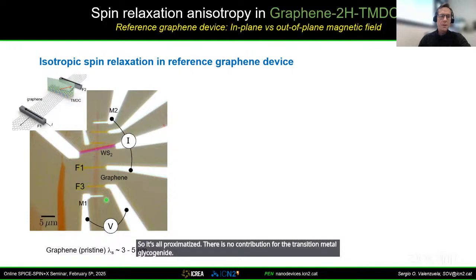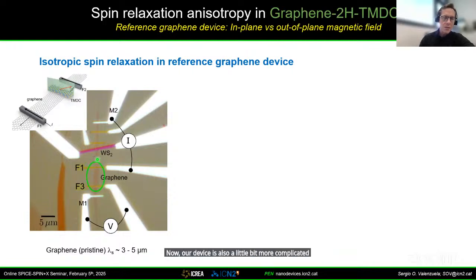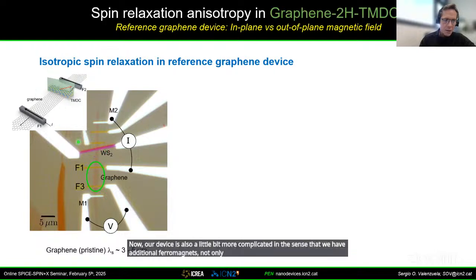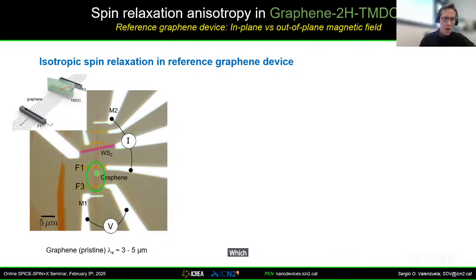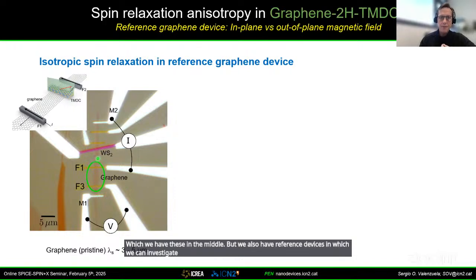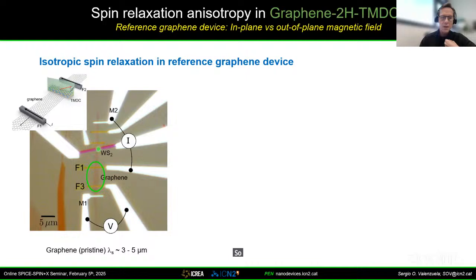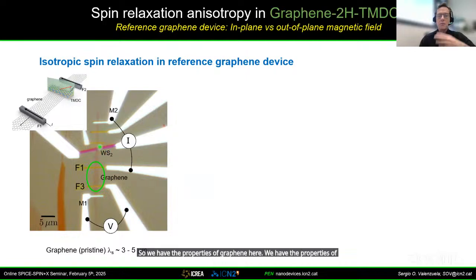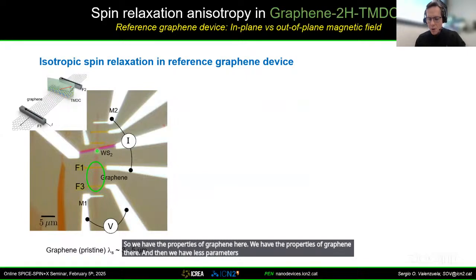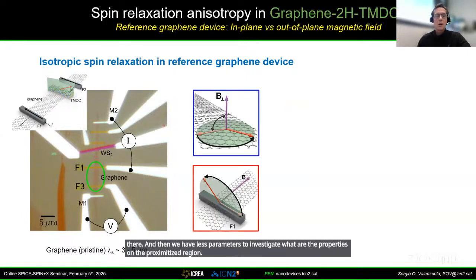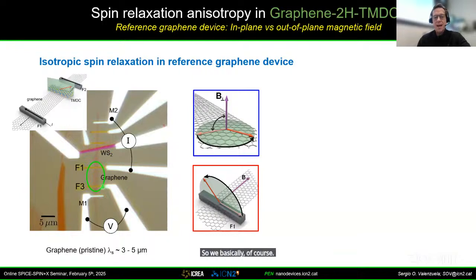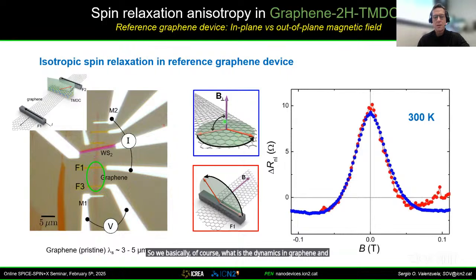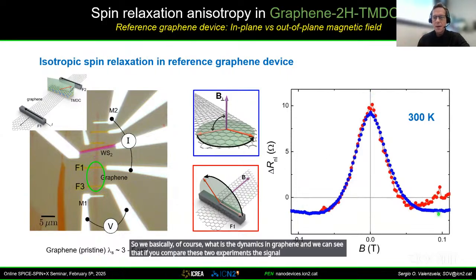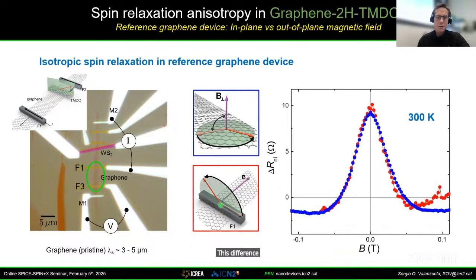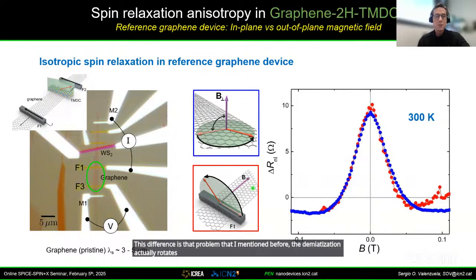Now, our device is also a little bit more complicated in the sense that we have additional ferromagnets, not only this part, which is here, in which we have this in the middle, but we also have reference devices in which we can investigate the transport in just bare graphene. So we have the properties of graphene here, we have the properties of graphene there, and then we have fewer parameters to investigate what are the properties in the proximitized region. So we investigate, of course, what is the dynamics in graphene, and we can see that if you compare these two experiments, the signal is pretty much the same. This difference is that problem that I mentioned before, that the magnetization actually rotates, but this is very well understood.